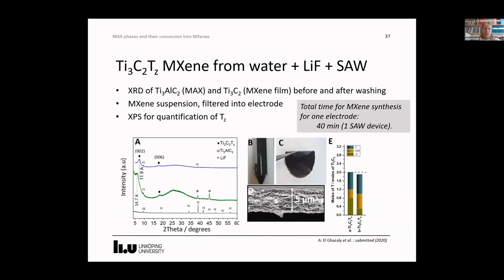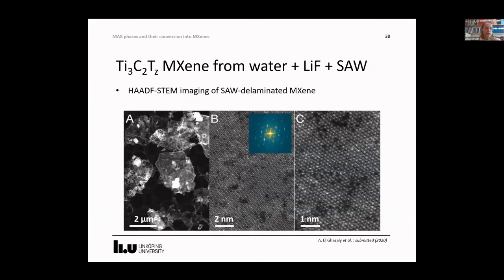An important result is that an electrode like this for further characterization is obtained in just 40 minutes using one surface acoustic wave device. The MXene formation is further confirmed by STEM. The low magnification image shows sheets of up to 1 micron, and B and C show the lattice-resolved hexagonal MXene structure with some vacancies that we are used to seeing.